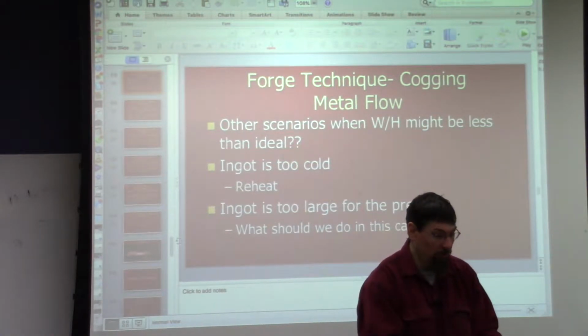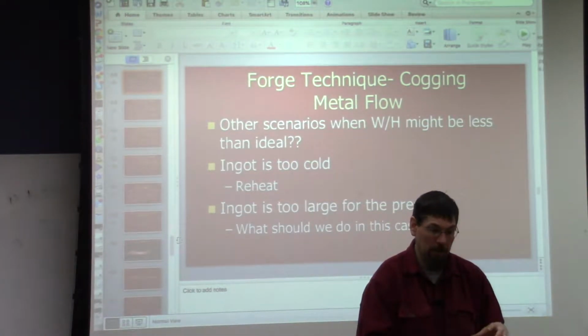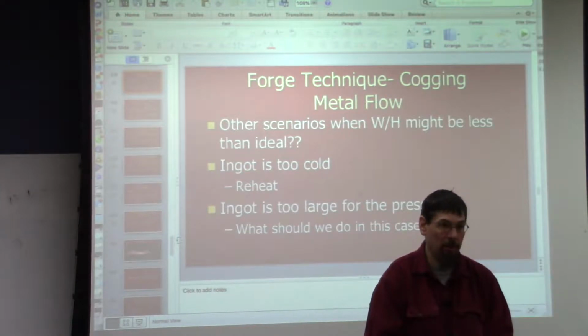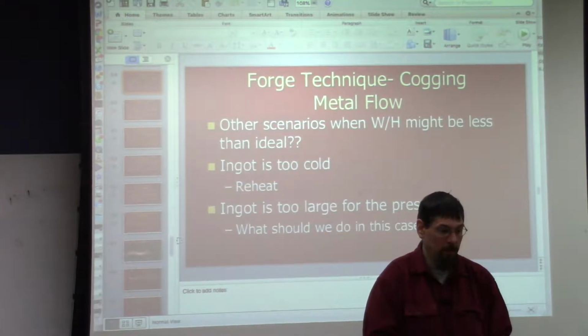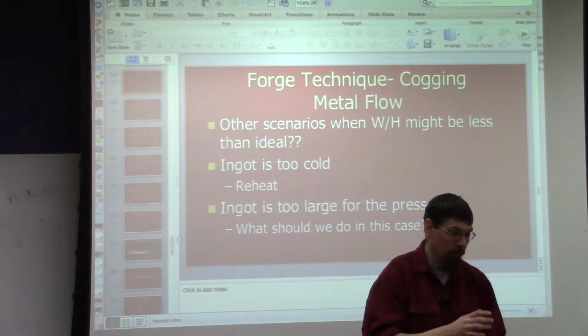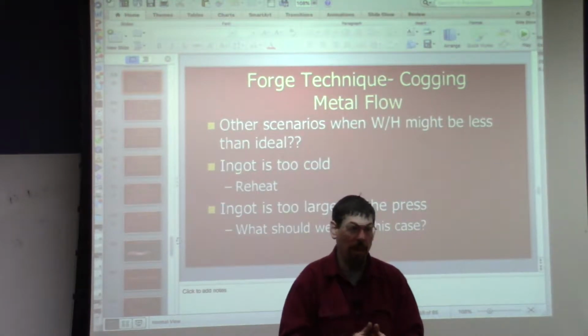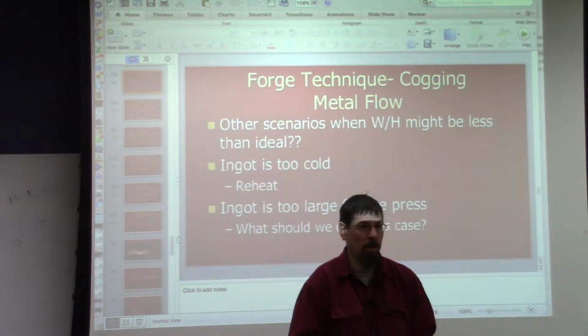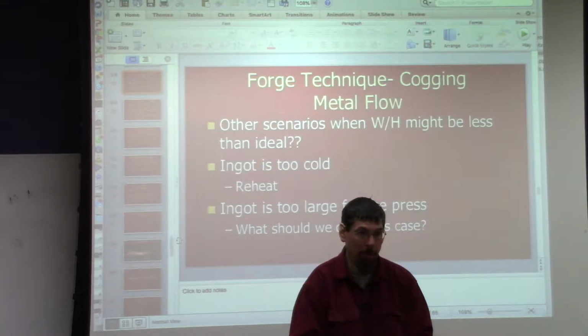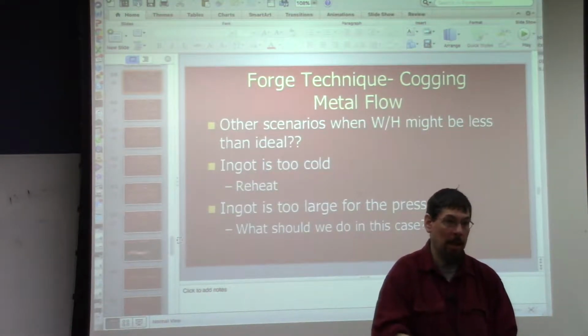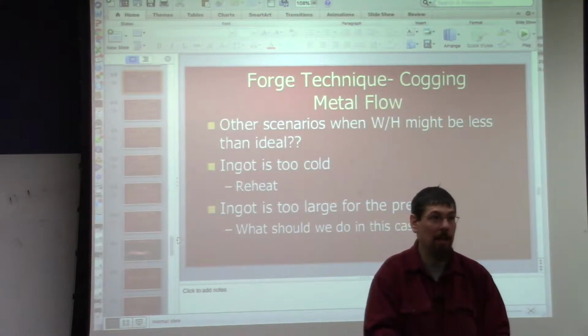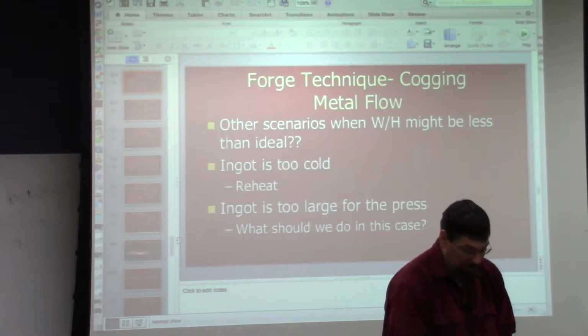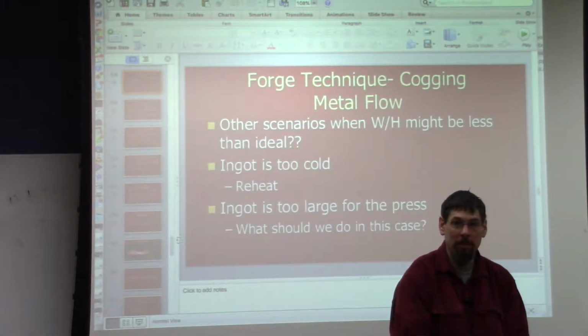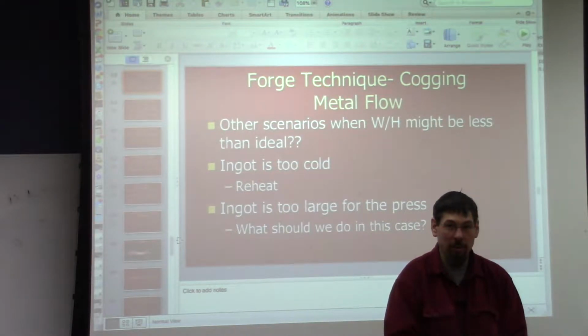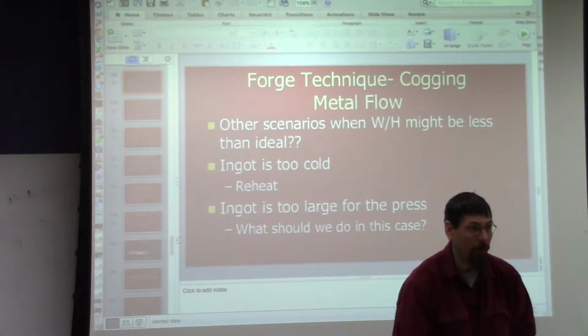And then they forged that shape into about a 26-inch diameter cylinder. In combination, between the two different forging steps, they had a little bit more than 3-to-1 reduction on paper. But because they didn't actually do the things that we talked about today, they didn't close up the holes that were in the ingot, so they're all left here. And when we did an ultrasonic test on this forging, it failed, and we cut it open, and it looked like I'd gotten a hold of a piece of Swiss cheese.